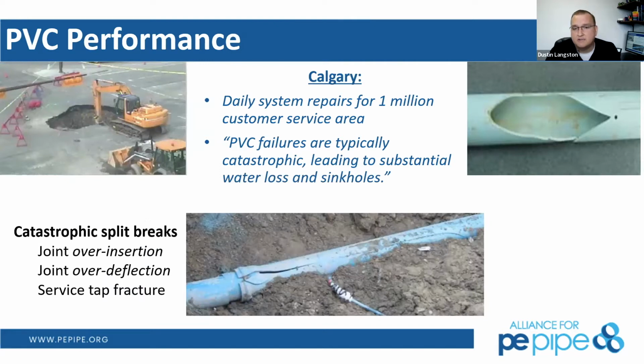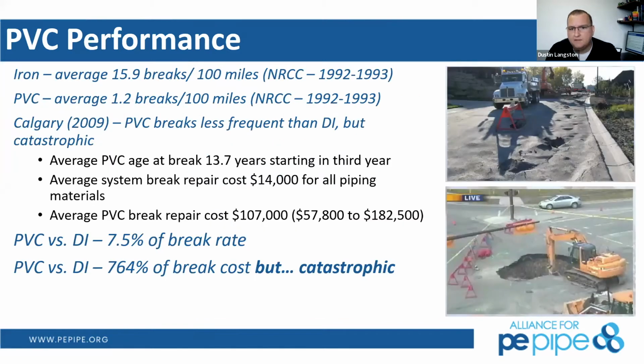The city of Calgary actually did a study here. This is about 5-6 years ago on their PVC system and their ductile iron system to see why it was breaking, what the costs were associated with those breaks, and how long service lives usually were on these products. And so city of Calgary, for those that don't know, in Alberta and Canada, over 1 million services in that city. And the findings of their report was ductile iron was by far failing more than anything else. Pinhole leaks, tuberculation, corrosion, average 15.9 breaks, so 16 breaks per 100 miles. PVC was breaking much less frequently, about 1.2 breaks per 100 miles.